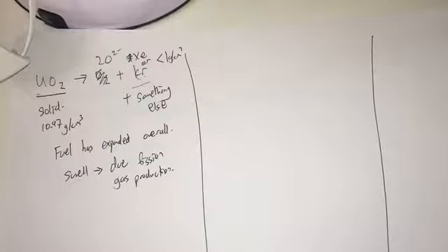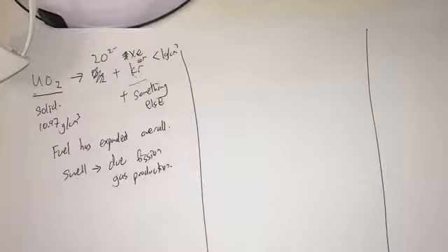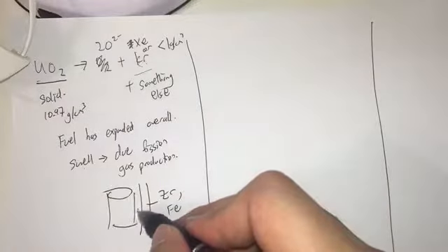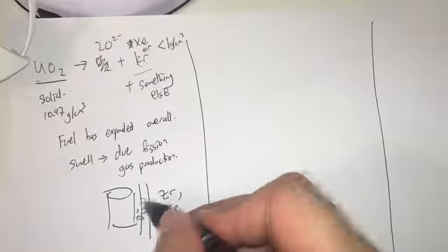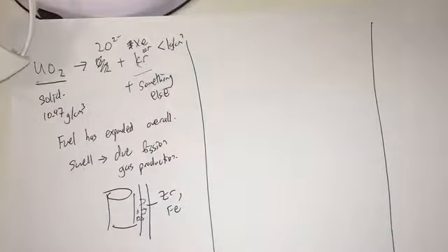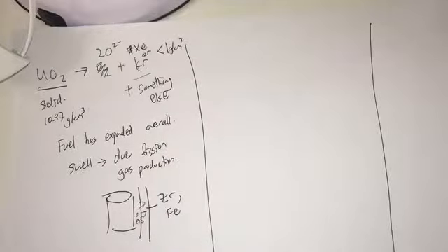Furthermore, since oxygen from the uranium oxide is now free, it can go and react with some other metals nearby. For example, if you have a fuel here and you have a cladding here, zirconium and iron will be here. If there's enough oxygen being created in this process, it will start to eat into the cladding. It will start to oxidize the cladding. Now that's a bit of a troublesome thing. So the cladding will become more brittle over time due to this interaction.